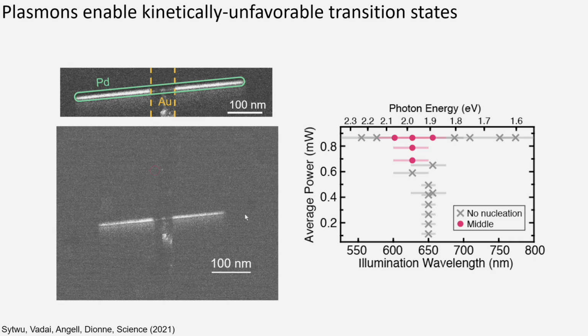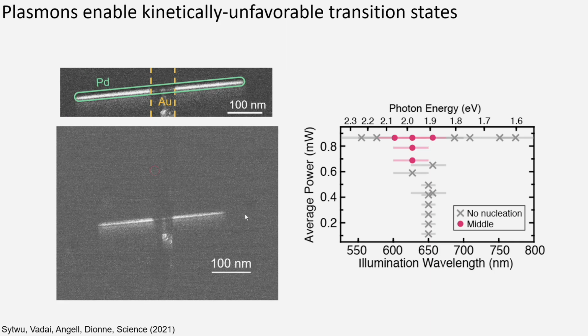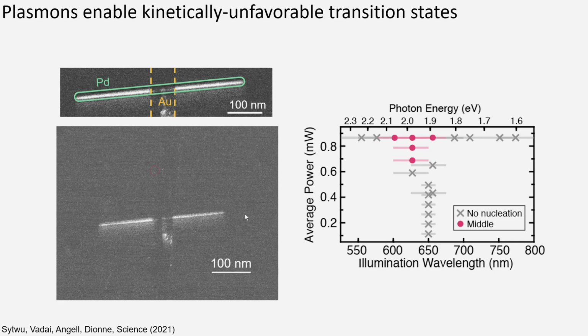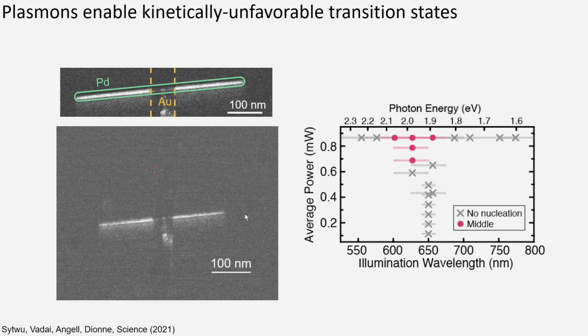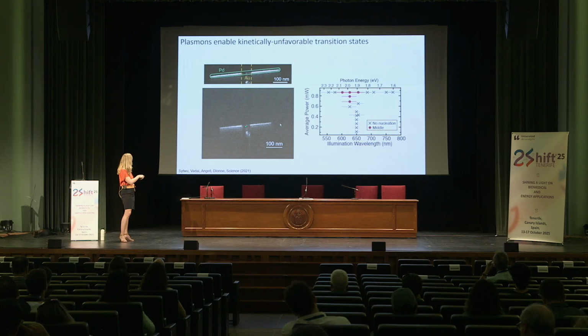Here we go. Okay, so we're doing dark field imaging and diffraction, looking at one of the crystallites in this palladium rod. Here's the gold bar. White corresponds to where the system is hydrogenated. So we turn the light on, and now you can see the hydrogen is basically leaving from the center of the rod. And then as the video plays, we'll turn the lights off, and you'll see that hydrogen is basically able to enter the system again, but it does so from the tips of the rod.